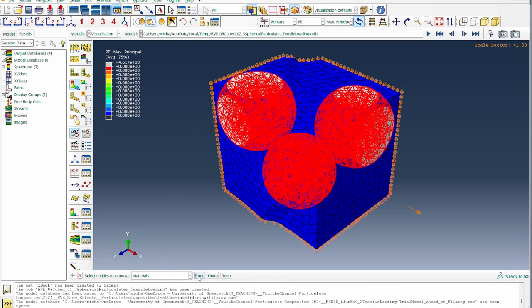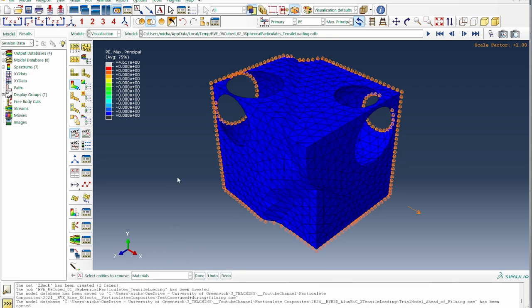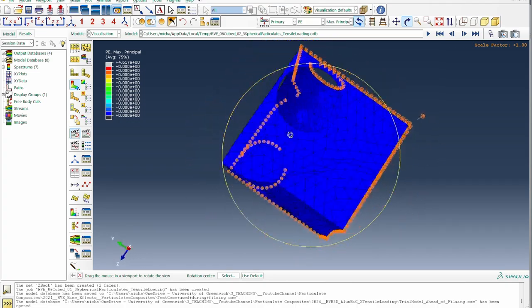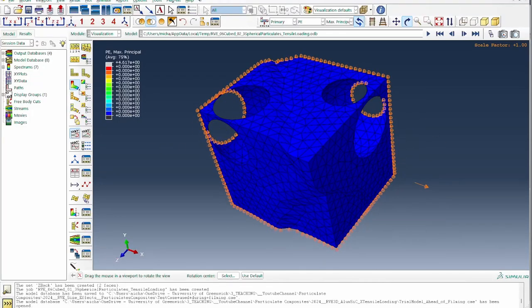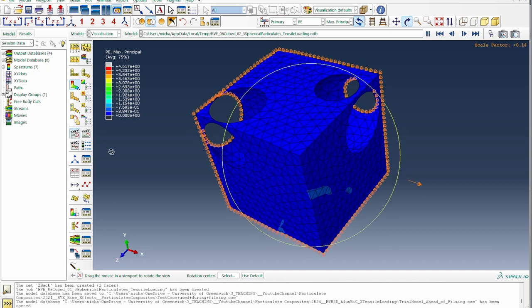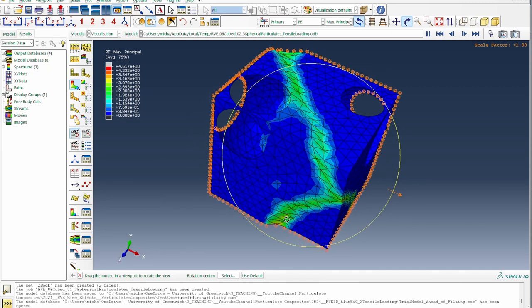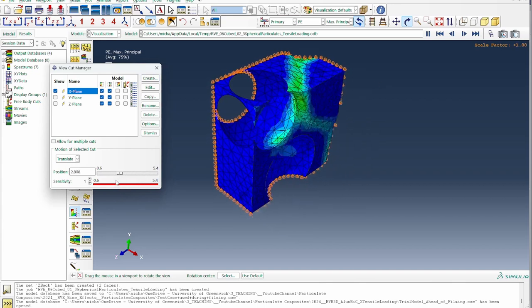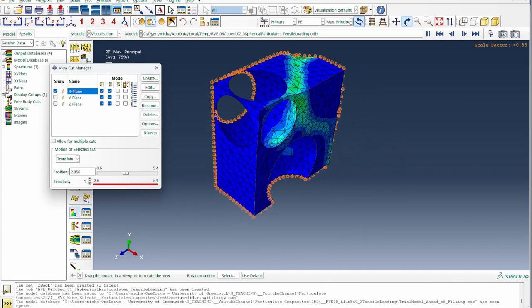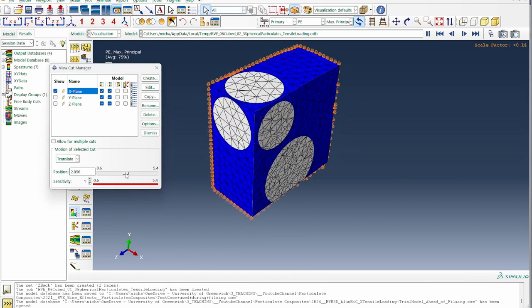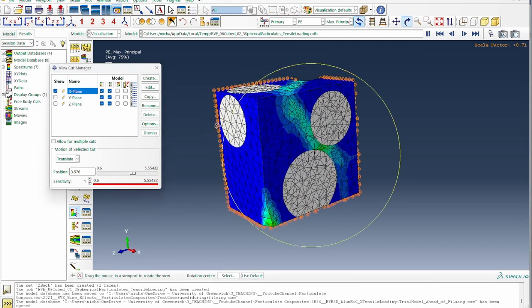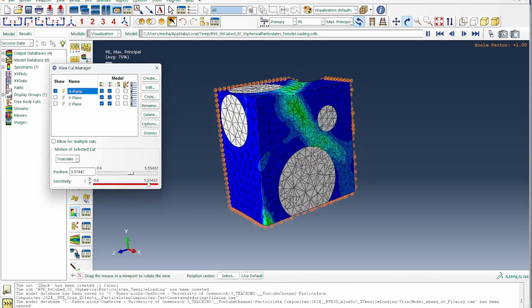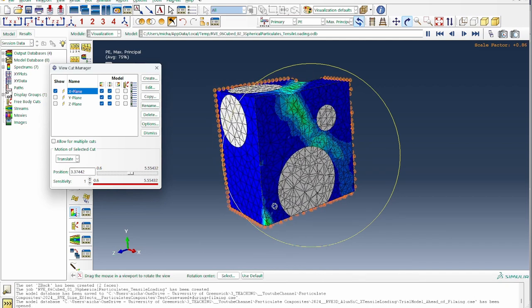The matrix is held securely at both constrained ends and at the base, and the deformation is clear. Cycling through the front and back of the structure, we can see internally how the shear zone is being transformed. The shear band initiates from the top, gets arrested by the particles, moves around them, and re-emerges at the other end.